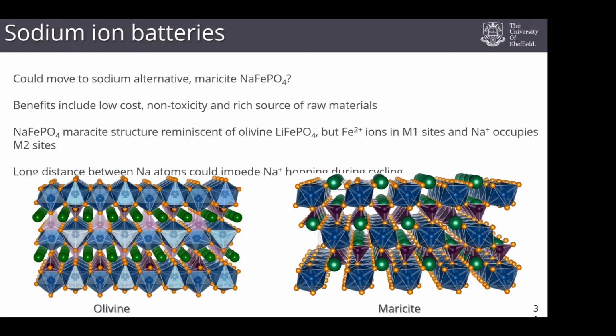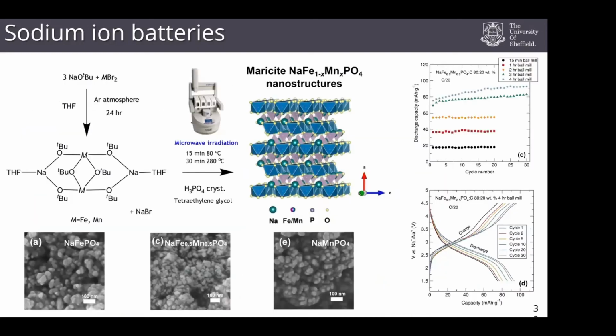So what can we do? Well, we can beat it up a bit and make it a little bit more disordered. I've talked about order being really important, but in this case, it's the opposite. If we can introduce some disorder, now we've got lots of potential pathways that sodium can move around, and you can start to get pretty good capacity out of these materials.